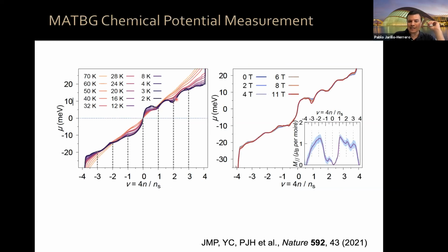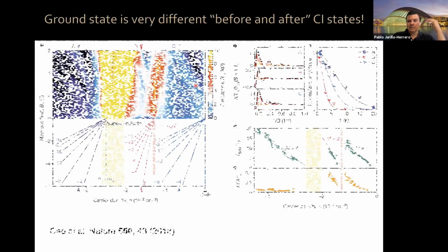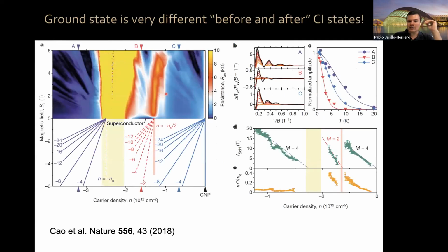By the way, one other thing that I wanted to tell you: as you can see in these chemical potential measurements, you can imagine what the derivative of this looks like. It looks like those peaks in the inverse compressibility measurements that I showed you in our work with Shahal Ilani. As you can see, something happens at each integer. Again, a cascade of phase transitions. This cascade of phase transitions is telling you again that before and after the correlated insulator states, the systems are very different, because there has been a phase transition in between.